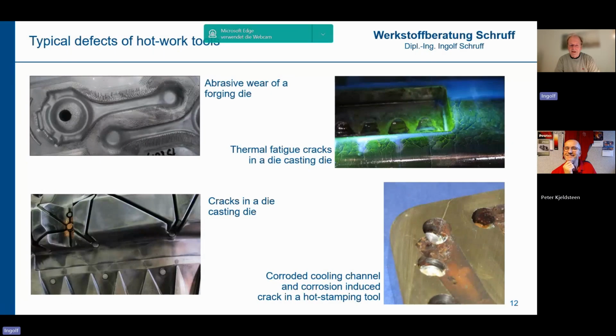But the corrosion resistance is getting more important, as I can show in one of the next slides here. All right, here in this slide, we see in the lower left photo a segment which had been cut from a cracked hot stamping tool. And what we see here, this is the working surface. And here we have the cooling channels which follow the geometry of the tool. And here we have a feeding water channel, and here we see a lot of corrosion. We also see brown. Yeah, it looks brown.